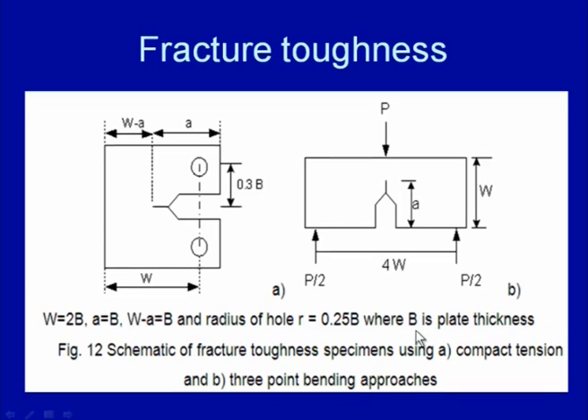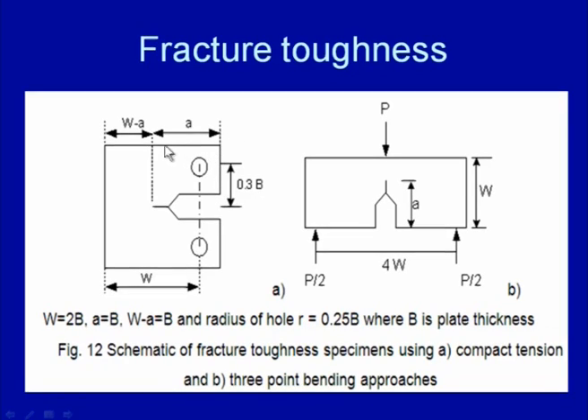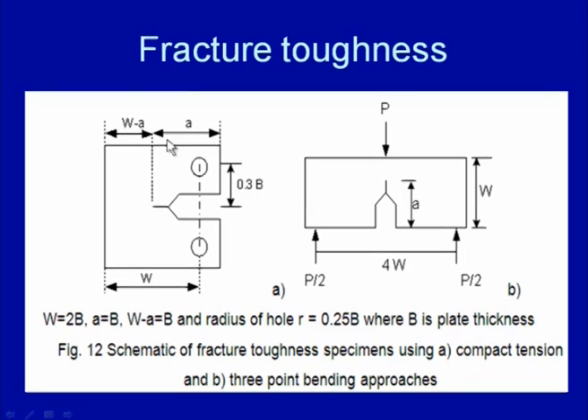So, B is the thickness of the plate, and W is the width of the plate measured from the center of the hole, that is kept around 2B, and then A is the crack length, that is this length, the pre-cracked length, measured from this edge. So, we first make a notch by machining, and then a crack is developed, and this total length is measured as A, and the remaining length where we do not have a crack is measured as W minus A.